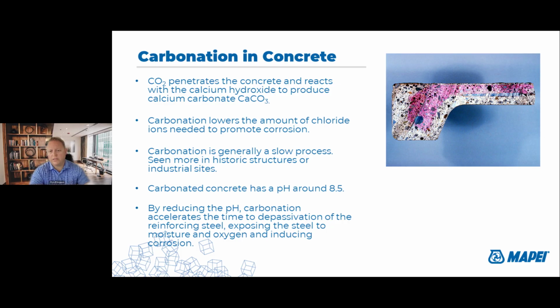Carbonated concrete has a pH around 8.5, where you compare that with new concrete, pH around 12, 12.5. One of the things you can use to see if you have carbonated concrete is called the phenolphthalein test. It's a dye indicator where they will paint it onto the concrete or spray it on. And if your concrete is pink, you're good. If it's clear, that shows that you have carbonated concrete, and then you can measure the depth that concrete has become carbonated. By reducing the pH, carbonation accelerates the time to depassivation of the reinforcing steel.